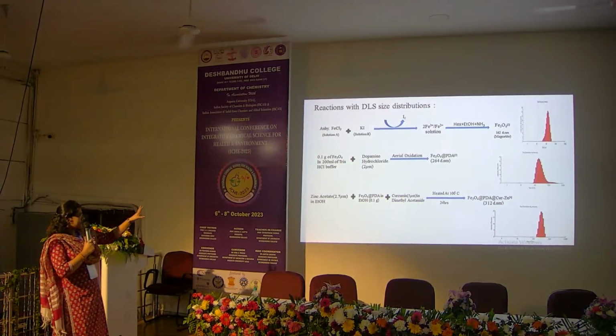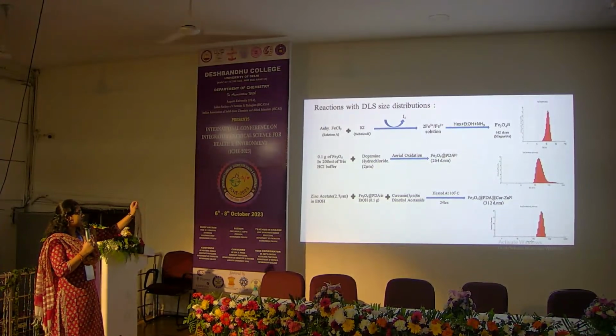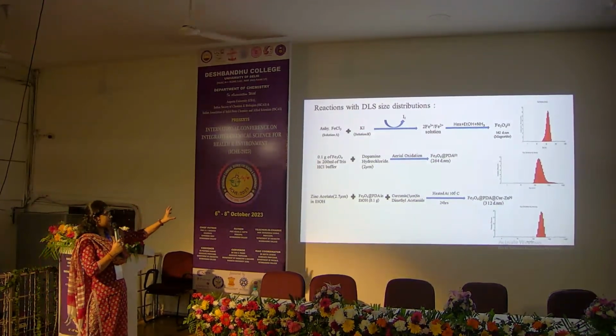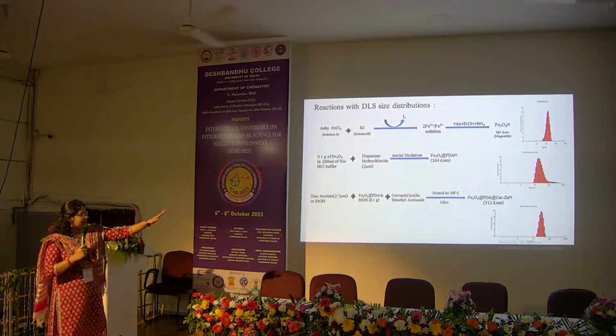And in the second process, I coated it with polydopamine. I added iron oxide to dopamine hydrochloride in the presence of tris buffer, and I coated it.